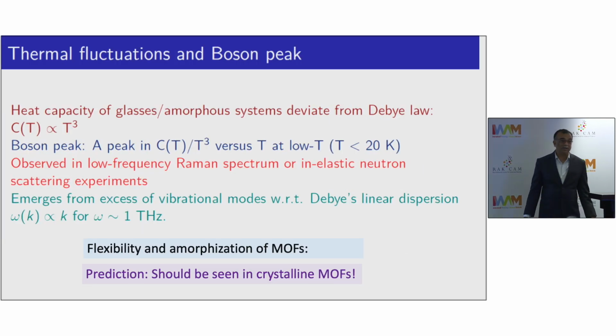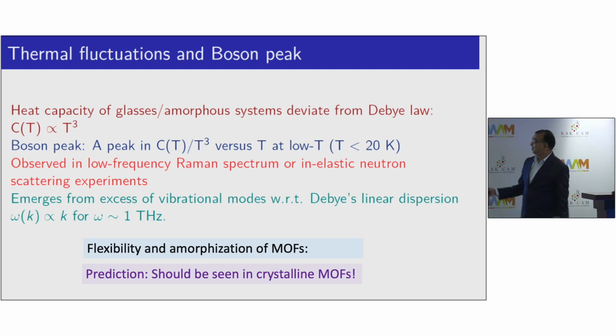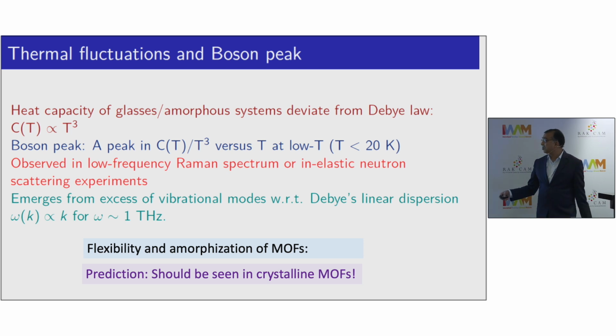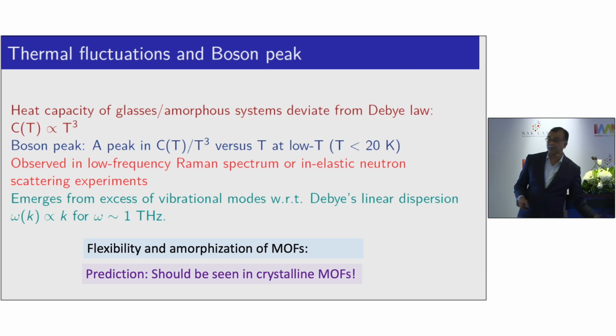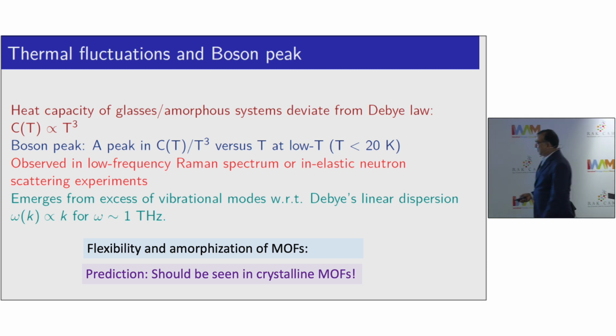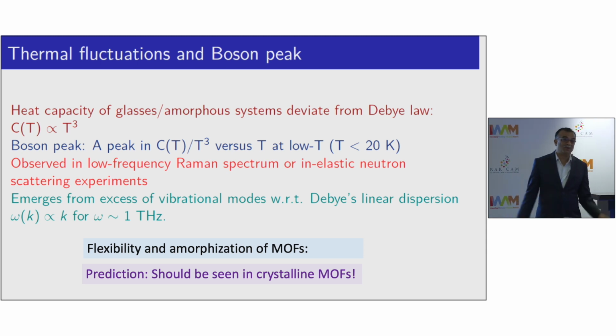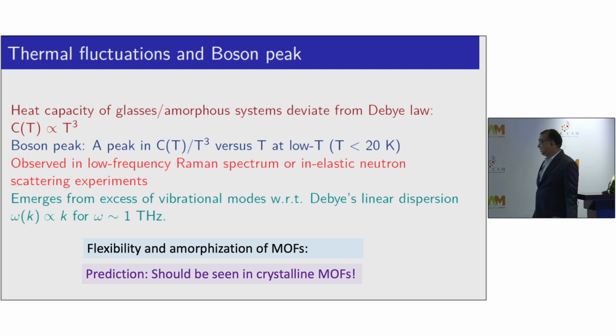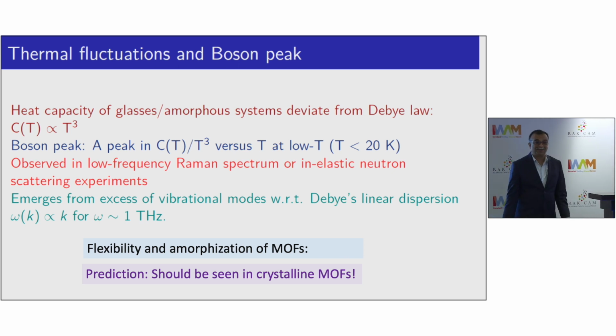So lastly, these phonons are also relevant to thermal fluctuations and specifically the boson peak, which is a feature in glassy systems where the specific heat deviates from the Debye law, the T-cube behavior of specific heat at very low temperature. If you plot C specific heat by T-cube at very low temperature, you see another peak, or excess specific heat, as it is called. That usually arises from vibrational modes present at fairly low frequencies, which are different from the linearly dispersed vibrational modes in crystals. Okay? So it appears that flexibility and amorphization of MOFs should be connected to each other through this language of phonons. And our prediction is that you should see a boson peak in MOFs as well.